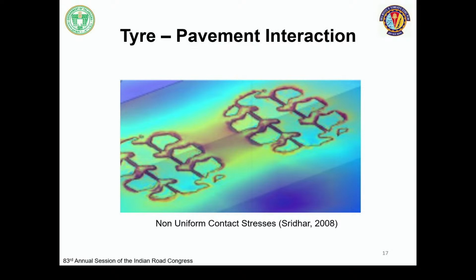It's not only the aging of bitumen, it is also the non-uniform contact stresses which cause this damage. In most cases, what we think is it is a circular loading, uniform loading. That is not true. It is non-uniform because of the treads itself. So when the surface binder becomes aged or it stiffens, this cracking is predominant.